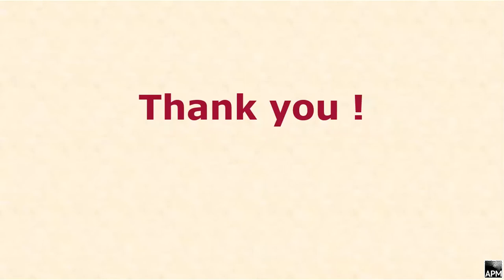First of all, thank you very much for your presentation. Only one question. You can see individual dislocations, so what in reality is the typical dislocation density when it reaches its maximum at the interface? The question is that these nanowires are very small in size, so we cannot speak about densities. In the cross section, there may be up to some dozen dislocations at the interface. If we consider the length of the nanowires, we can of course have some equilibrium densities, approximately one dislocation loop per 10 nanometers. It's very high. Okay, thank you.